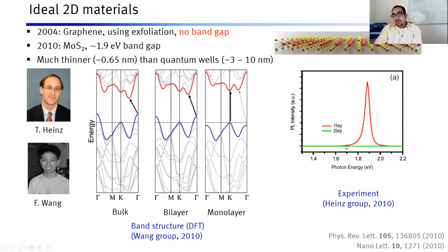For example, for a bilayer, you don't see much emission at all. In fact, on these scales, you do not see it, but for a monolayer, it's very bright. Suddenly, you start to see a lot of light emitting out, because now it has become a direct band gap material. This was seen in 2010, and this is where the field kicked up. In fact, this paper, I think it already has more than 13,000 citations or something. I will have to check what's the latest.